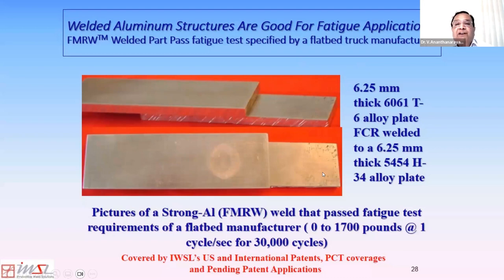And these grip marks were made when these welds were fatigue tested to a specification specified by a flatbed truck manufacturer in Canada. And these were loaded from 0 to 1,700 pounds. My apology for the American units here. That's about 0 to, I would say, a 770 kilogram load at 1 cycle per second for 30,000 cycles. And the welds don't even look like they are tested. And these welds pass the fatigue test very comfortably.